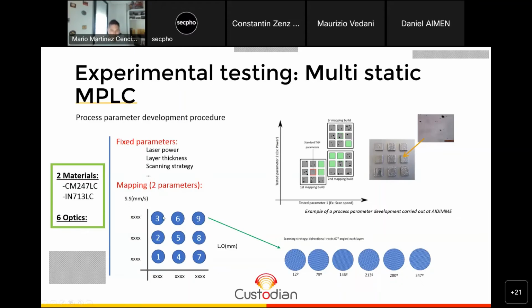Basically, we set up to 9 coupons arranged in a square like this, and then we set 2 parameters that will vary in this design of experiments. In this case, for instance, it is the scanning speed and the line offset, which is the separation between scan tracks, right? And the rest of the parameters remain fixed during the process, so that we can analyze the impact of these variables during the processing of these materials. And for all the experiments, we followed a 67 degree angled strategy between layers. So it means that scan tracks are rotated 67 degrees each layer, and a bidirectional approach.